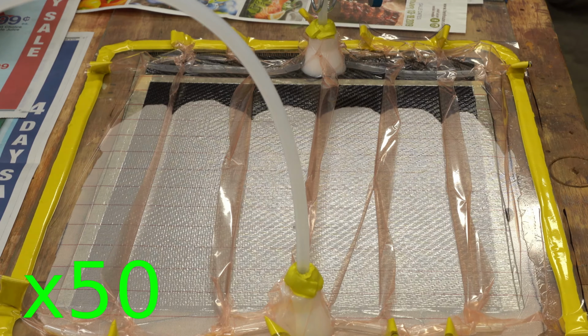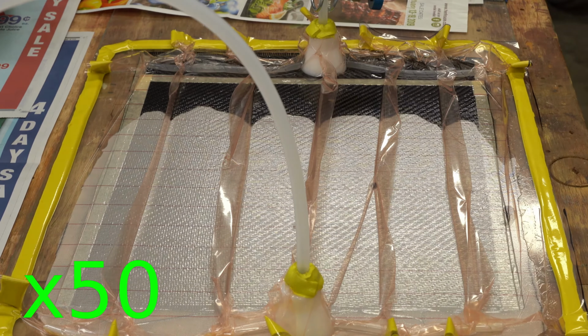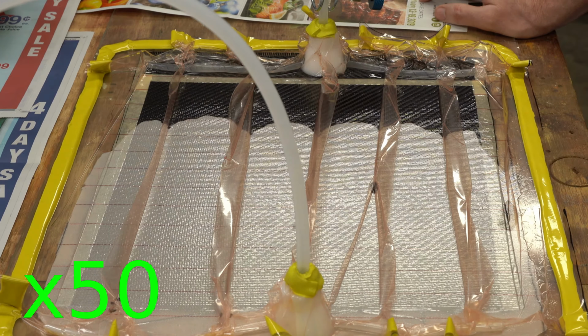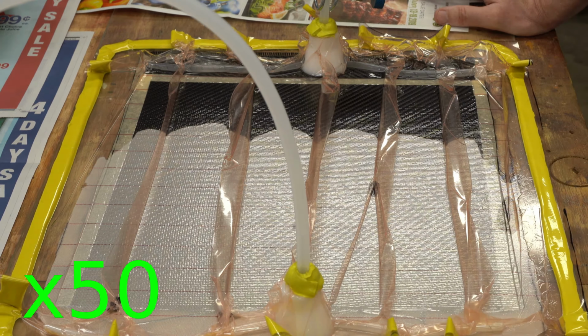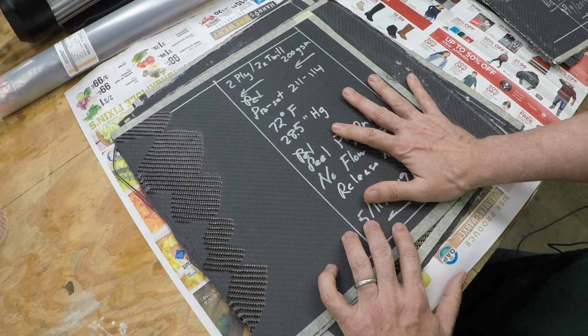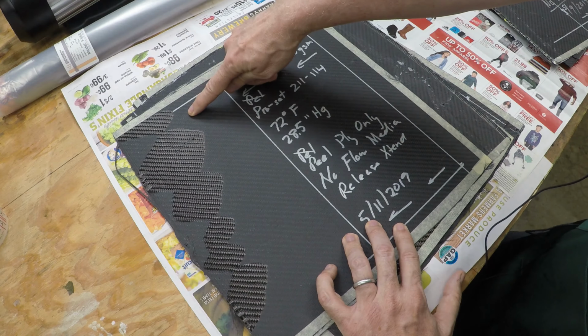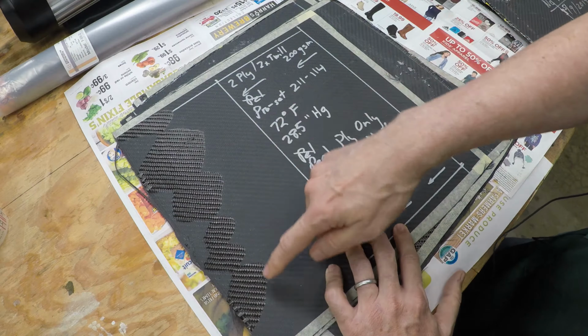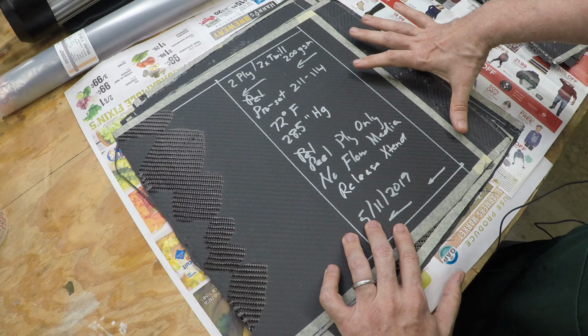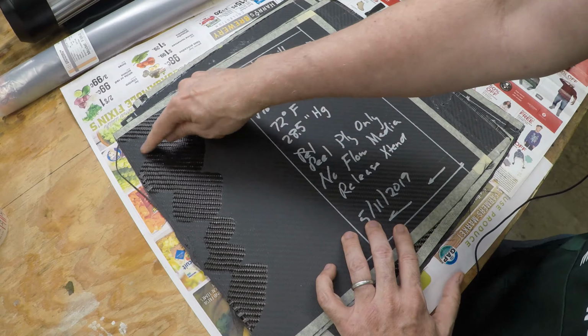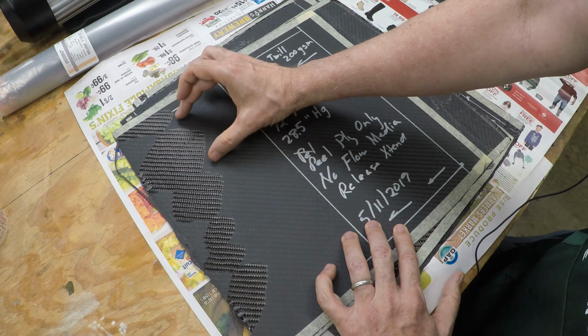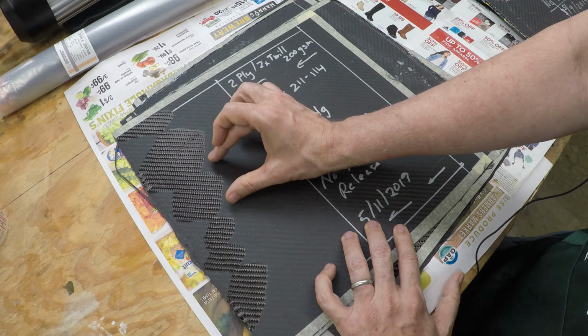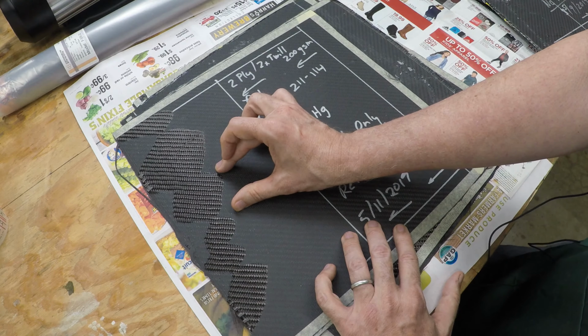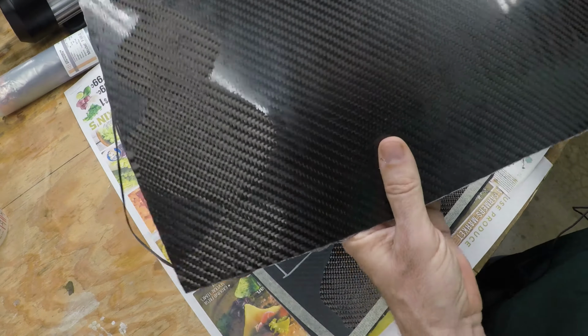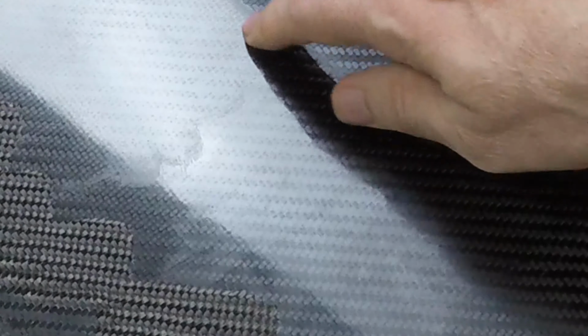So that was my next test. On this test, it's the same as the last one. It's just that I intentionally put those wrinkles in the peel ply. And I put 5 wrinkles in them, and you can actually see where they are on the back of this test. There was one here, one here, one here, and one here. That resin did flow better down through where those wrinkles are. The problem is that it didn't propagate sideways enough to help fill in the weave of the cloth. But I still got a fantastic finish.